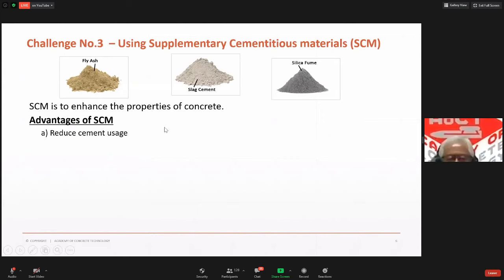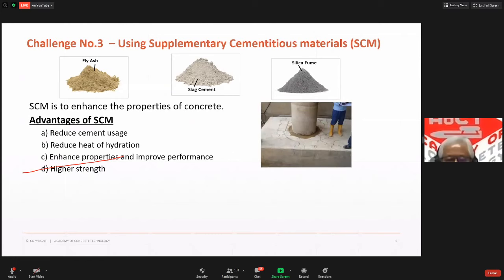Every ton of cement you produce is equivalent to almost a ton of carbon dioxide into the air. So by using all this, you help. We talk about sustainability, that's one thing. And the second thing is it actually reduces heat of hydration, especially when you're doing very thick slabs, maybe about a meter thick. When you do any thick concrete, what happens with OPC? For example, this could be a pile cap, it could be 1 meter thick, or even a basement slab. So what happens when you're doing such a thick slab using OPC?